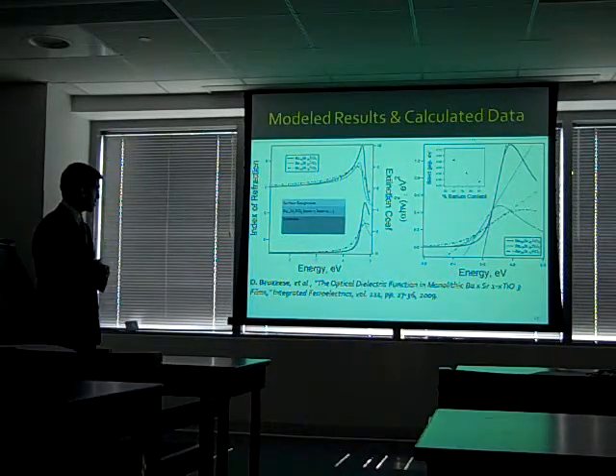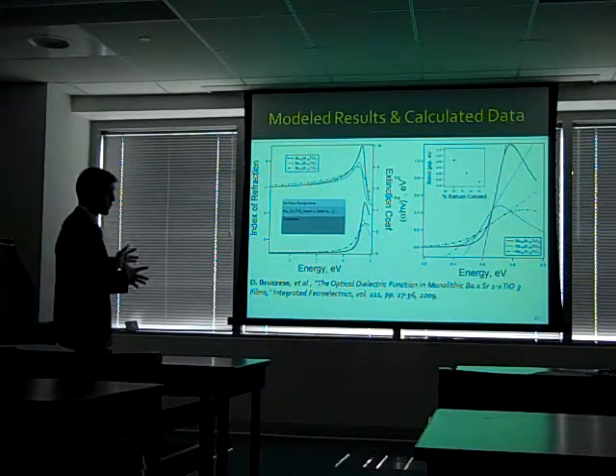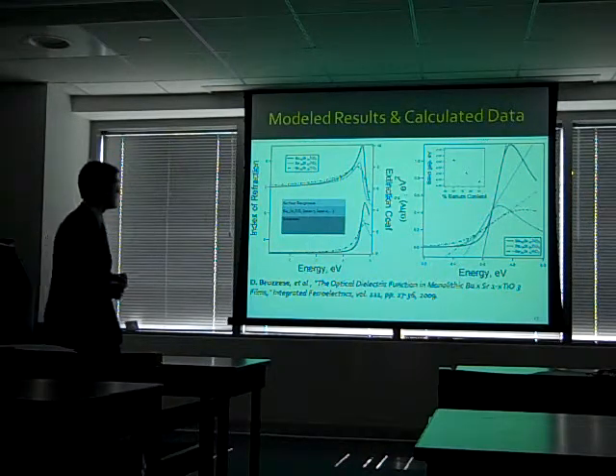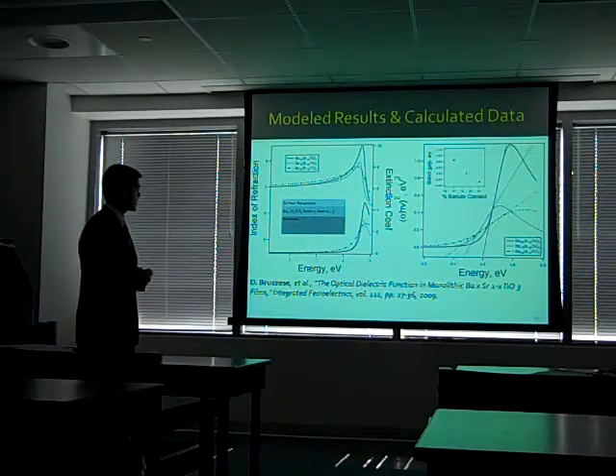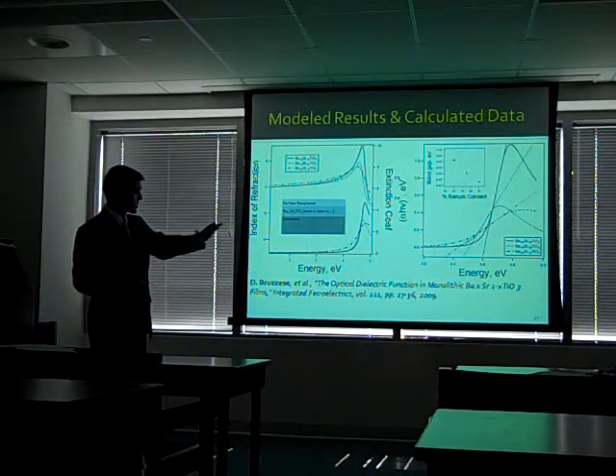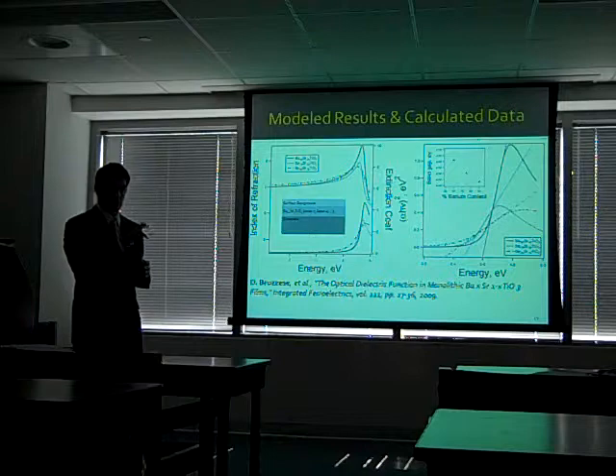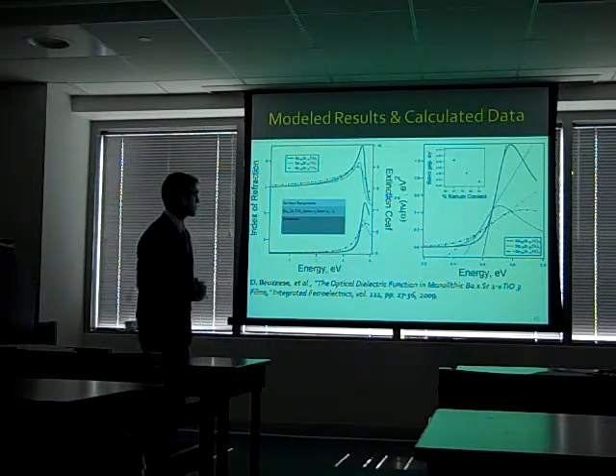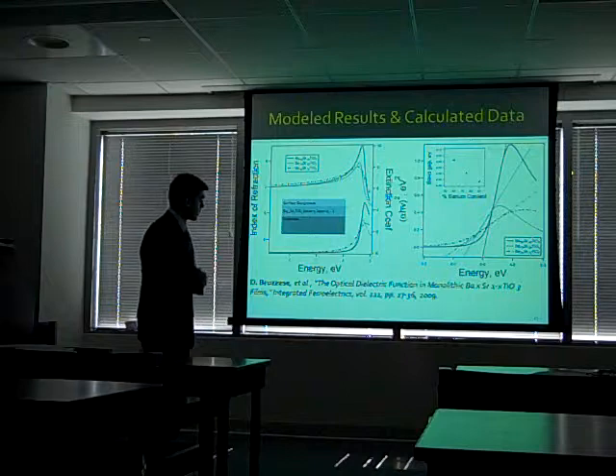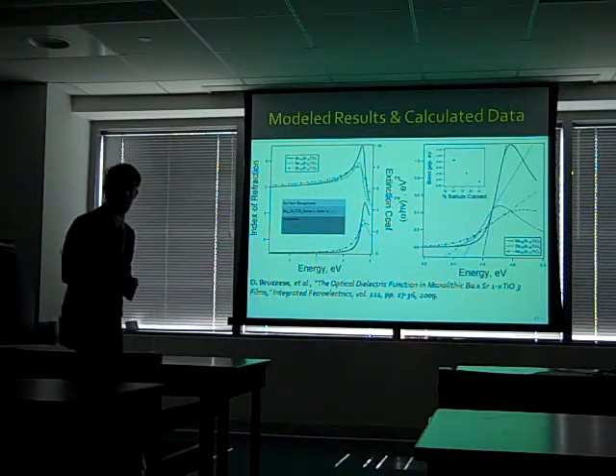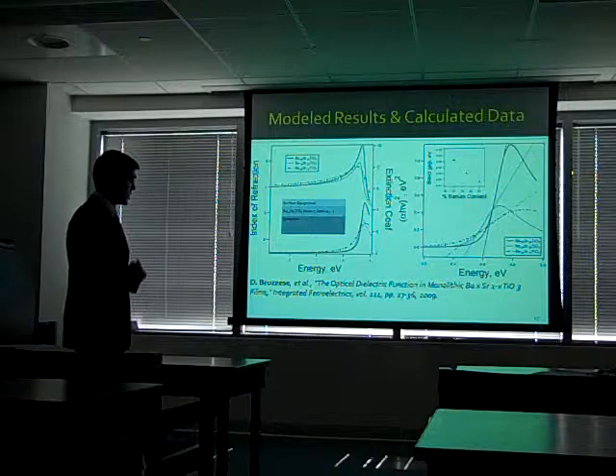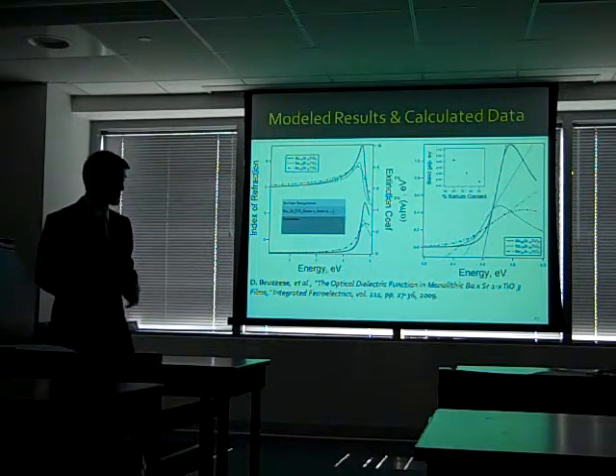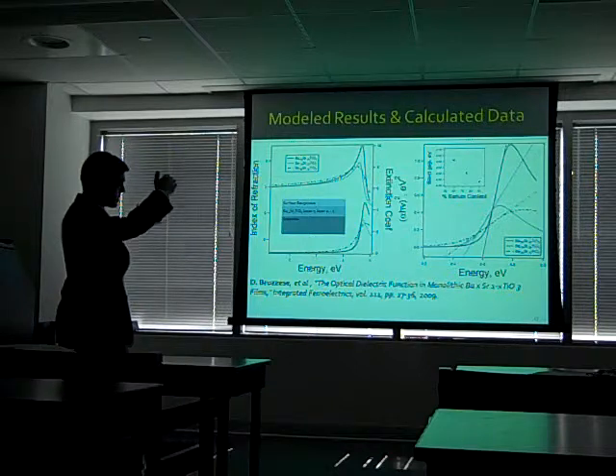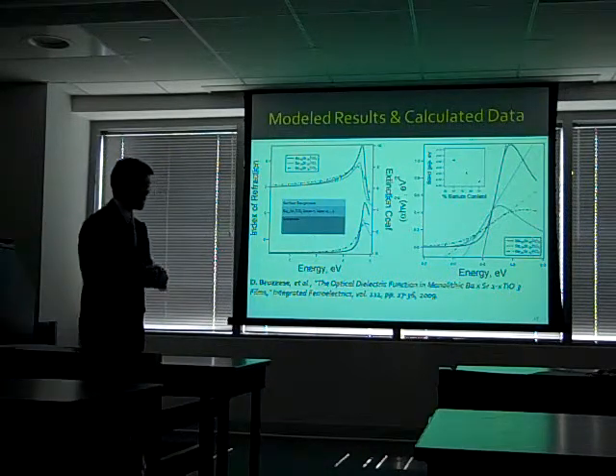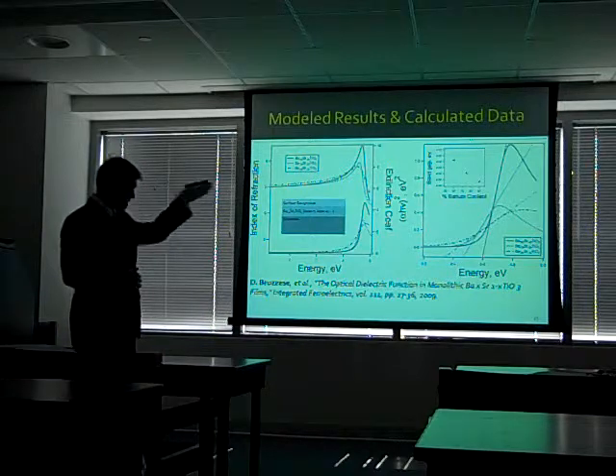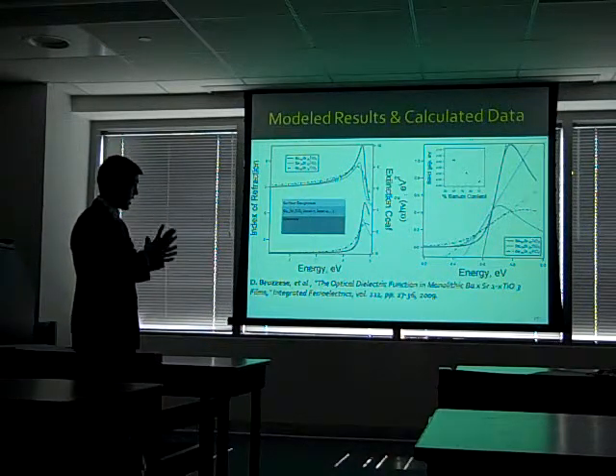These are some results that were recently published on this work. Again, to this point, we've only been talking about characterizing single layer films. So this first figure here shows the optical constants, the index of refraction and extinction coefficient, of 3 different compositions, 3 different single layers. And this is the model that I used. And then on the right side is the Tauc plot for those same samples. And you can see, again, the extrapolation to the x-axis. And the inset there shows the dependence of the band gap on the barium concentration. And if you remember from before, this is similar to what Panda et al. found.